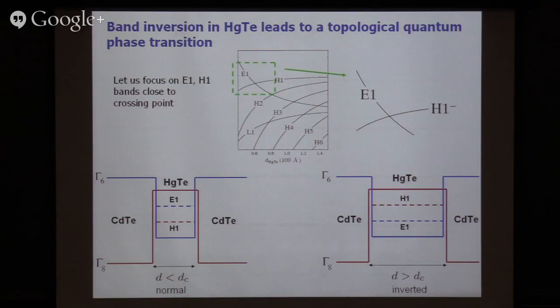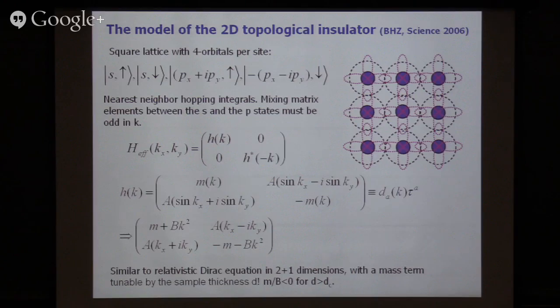So now this enables people to construct a very interesting system. You remember from the previous chart that cadmium telluride and mercury telluride are very well lattice matched. One is an ordinary material and the other has this very interesting band inversion. So as you change the width of the quantum well, you can go into limits where the S level lies above the P level, but then go through a phase transition beyond which the P level will go above the S level. And so now we constructed a very simple model back in 2006.